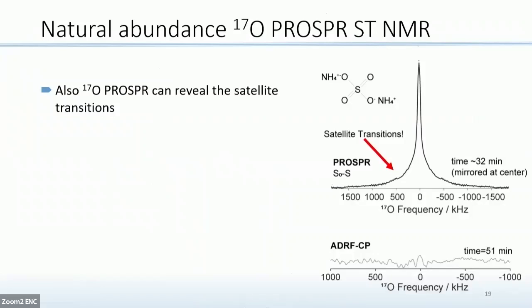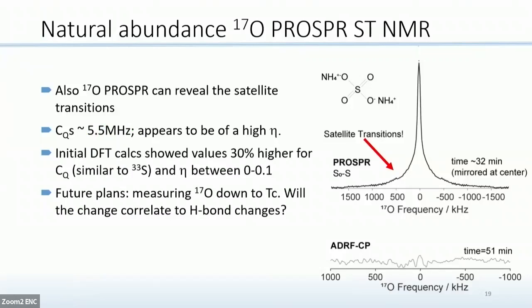So then also, we wanted to see if we can get similar information on oxygen, and this is the powder sample. This is not a single crystal. And we measured this at 2 different offsets. According to the satellites, we estimated the CQs at about 5.5 megahertz, and they appear to be high eta. This is in partial agreement with some DFT calculations. And we're looking forward to trying to measure the oxygen down to the critical temperature and see if it correlates to the hydrogen bond changes in this material.